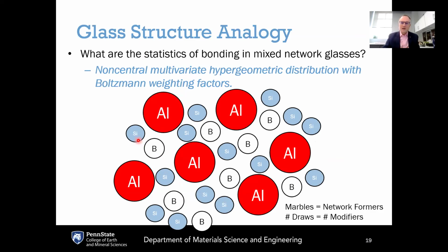So entropically speaking, which ones are more favorable? From an entropy point of view, the more favorable ones are just the ones that you have more of because they have a greater possibility of being drawn. But if you then have, say, more favorable energetics associated with alumina, each individual aluminum atom is like a larger marble because each individual one is more likely to be drawn, and that is the energetic effect. So we have this competition between energetics and entropic factors, and when we put it all together, the statistical distribution is called a non-central, multivariate, hypergeometric distribution, and it has Boltzmann weighting factors.